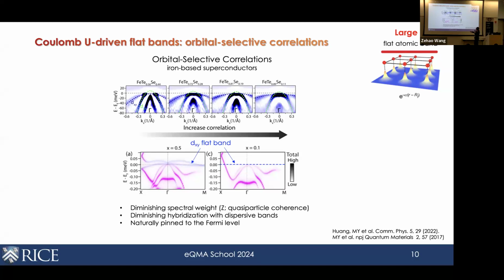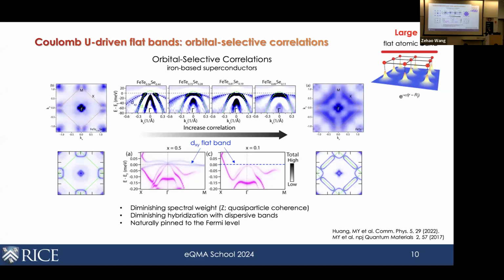And so therefore, the hybridization with the dispersive states gets turned off, so that in this regime, if you look at the Fermi surface, there's actually a reconstruction of the Fermi surface. This is the calculated Fermi surface, which induces a new pocket around the zone boundary. And this is what we observe experimentally, the change from one to the other, which is consistent with this picture, that you have this correlation-driven flattening of the band.